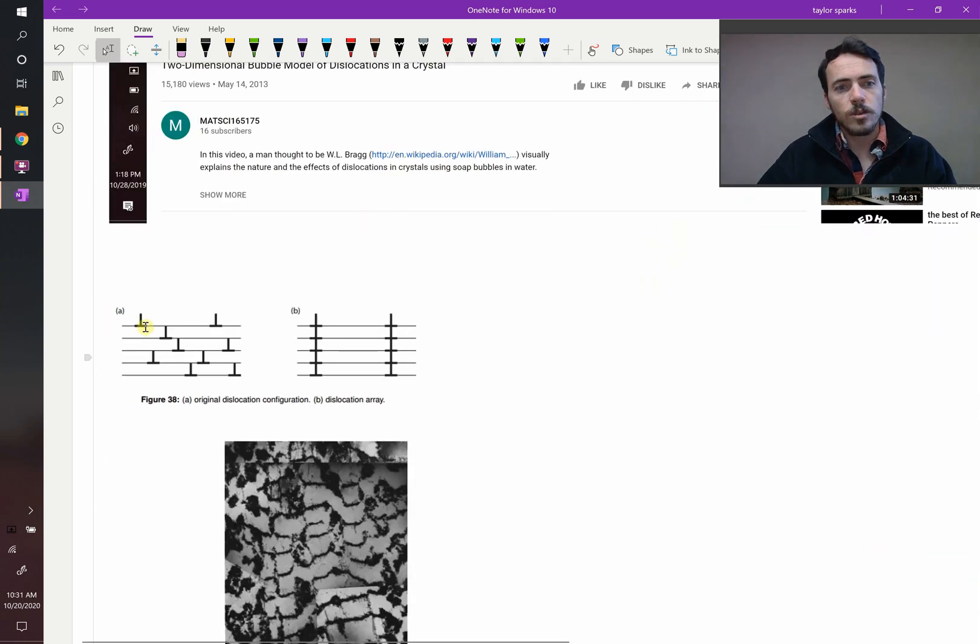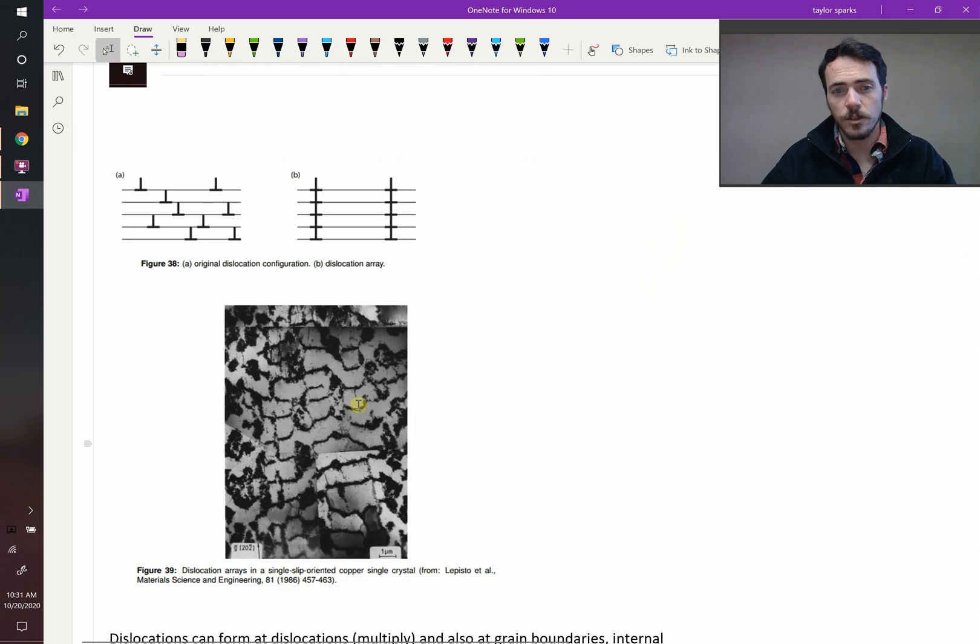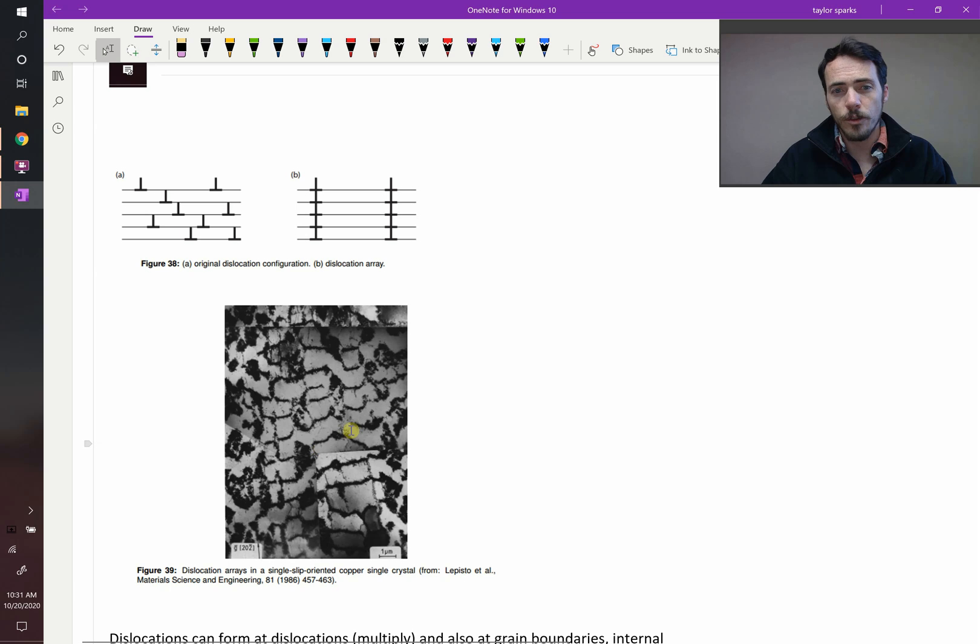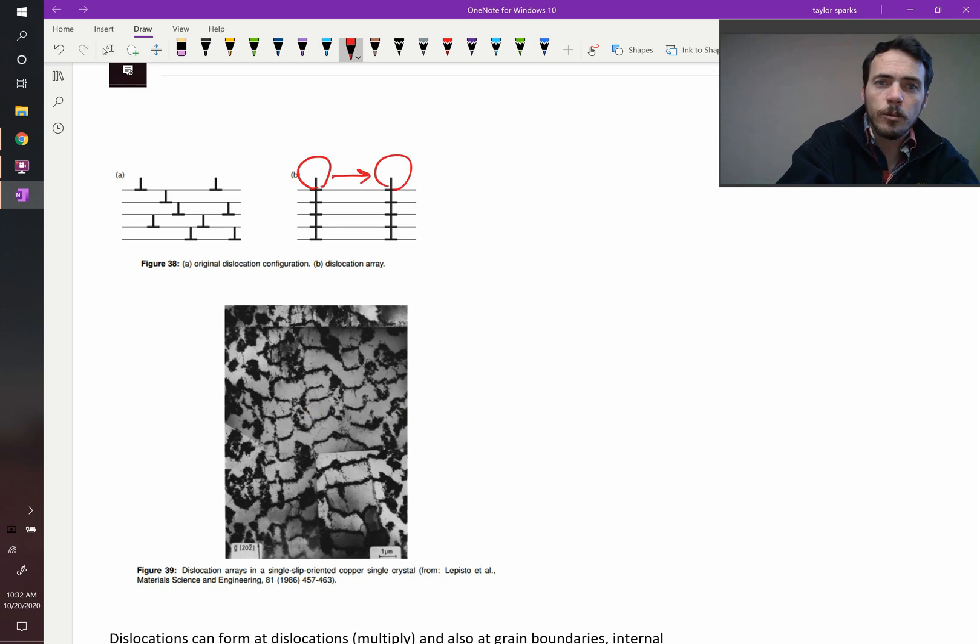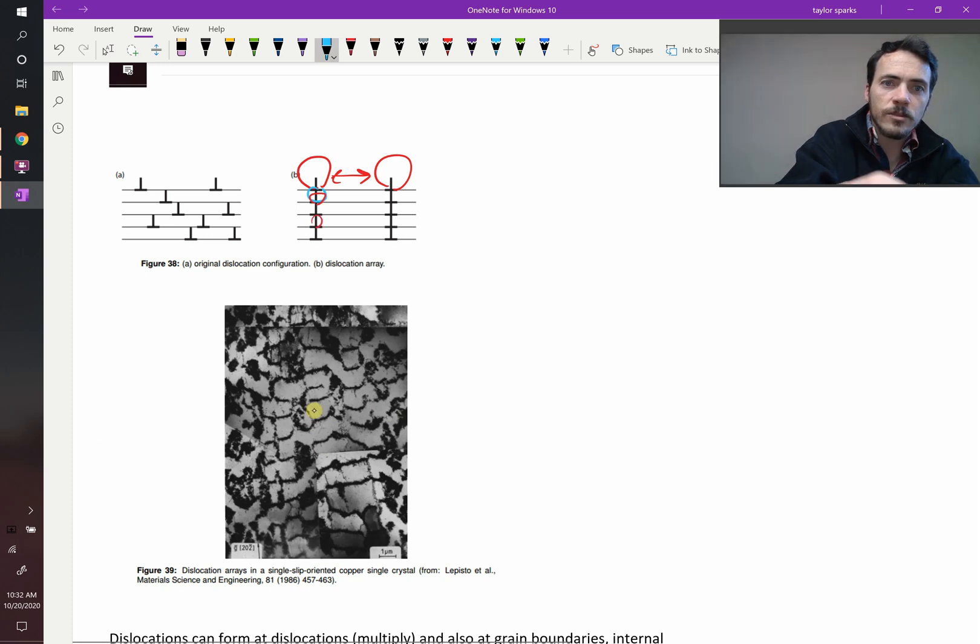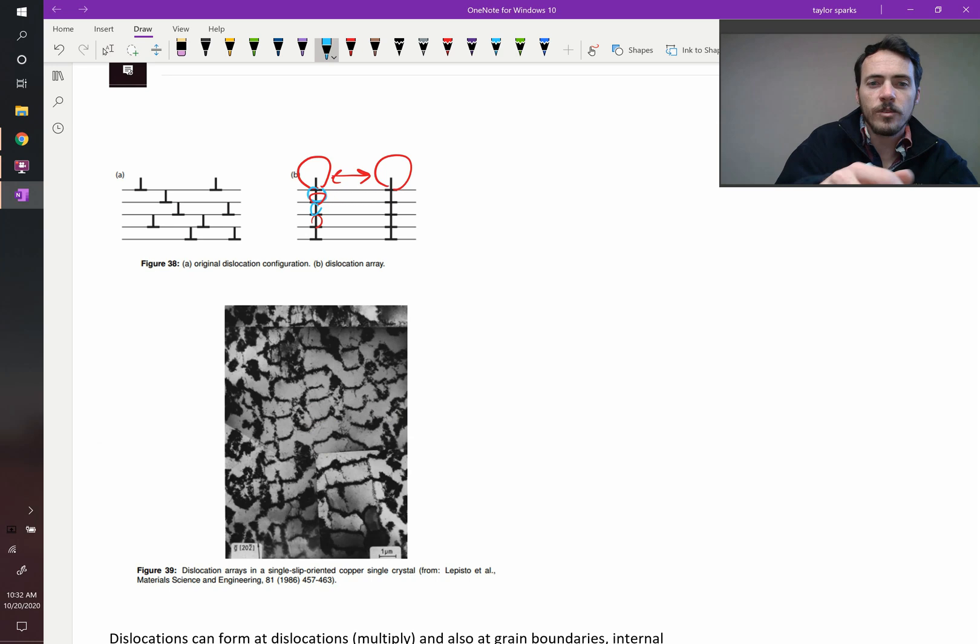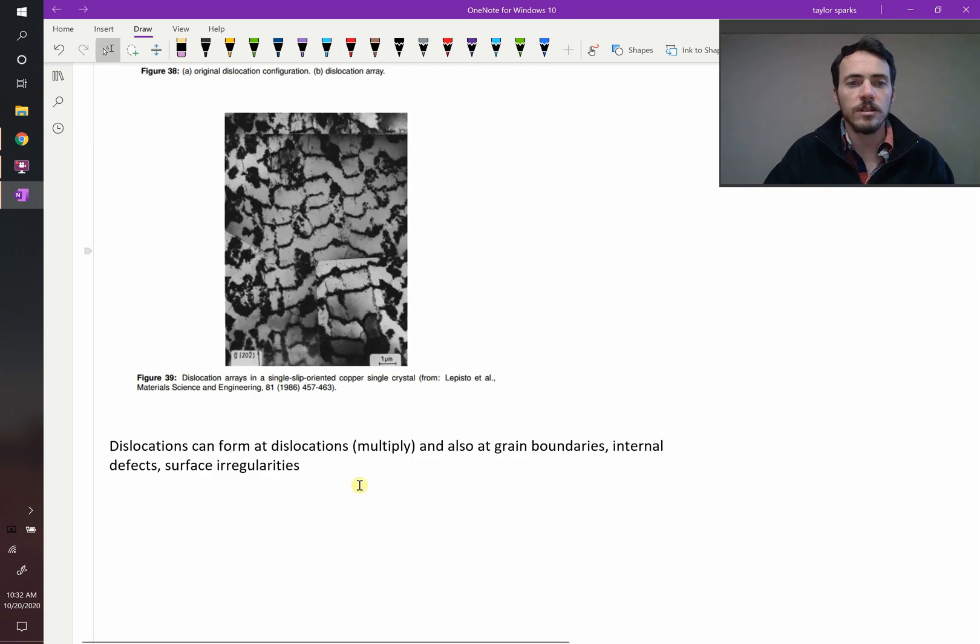So again, dislocations will stack up vertically. You can see these bands of dislocations in materials. If you etch a material, then you can get it to preferentially dissolve the regions near these dislocations. And you can see that they have a certain distance where they separate each other. Why are they separating? Because again, these compressive regions are repelling one another, but you also get this interaction between these compressive and tensile regions so they're stacking up. So that's why you get bands of dislocations in a material.